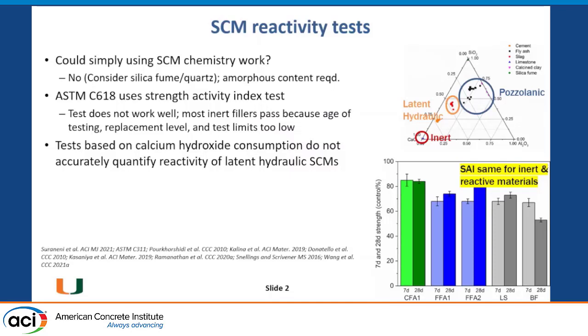You can measure calcium hydroxide consumption and that is important. Lots of tests measure calcium hydroxide consumption, but they do not accurately quantify reactivity of latent hydraulic SCMs because, as we discussed, they don't need calcium hydroxide to react. There are specific tests — for example, the Chapelle, Modified Chapelle, and Fratini — which do this. I'll directly discuss calcium hydroxide consumption.